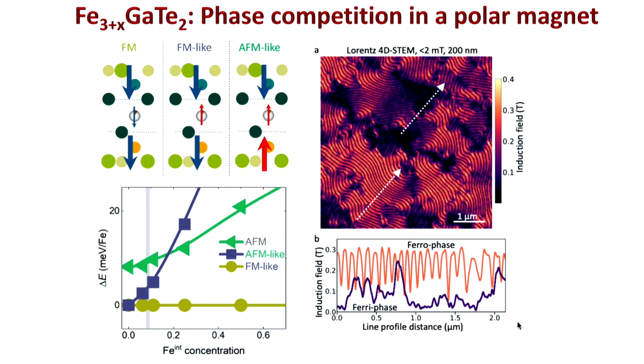Now, if you look at it schematically, those are three different phases: the ferromagnetic phase, which has the moments in the layers and the intercalated layer. Or it could be ferromagnetic-like, where this could be antiferromagnetic, but that moment is smaller compared to the main moment. Or it could be purely antiferromagnetic-like. Now, all of them are competing. They're not dramatically different in energy scale, so they're competing with each other.